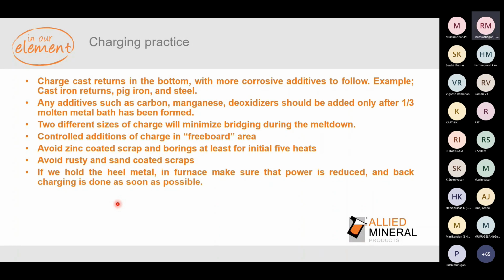So coming to the charging practice again, we recommend to charge the returns first, followed by pig iron and steel. Any additives such as carbon and Mn should be added only after 1/3 of the molten metal is formed, or at least 50%. Actually, 50% is the recommendation, or otherwise at least 1/3. Try to have different sizes of charge to avoid bridging, because once bridging happens, it's very hard for the upper scrap to get in, and then your bottom-side metal is going to get superheated, causing the refractory to run out. Avoid zinc coated scraps, rusty scrap, and sand coated scraps.